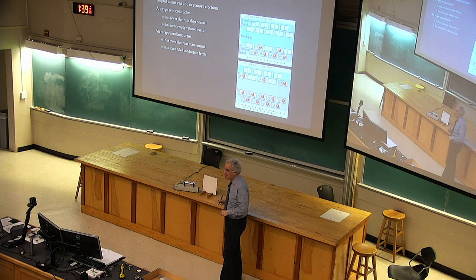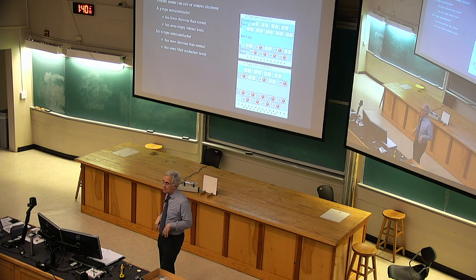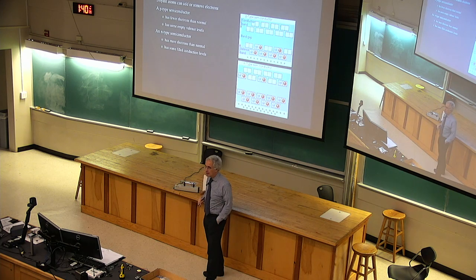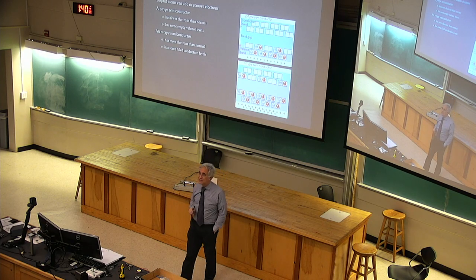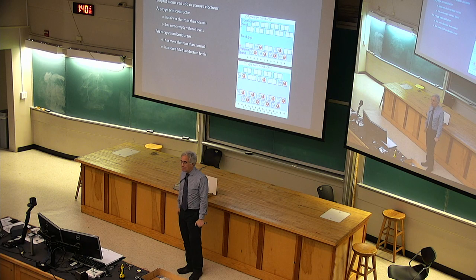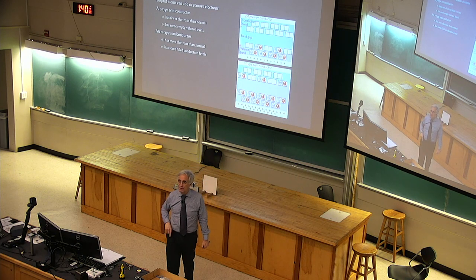All right. What if you start mucking around with the silicon? So I do have silicon in mind when I'm talking about this, but there are other semiconductors, some of which are important and in common use. But we can stick with silicon, it's good enough. If you take silicon and you remove a couple of atoms from the overall solid and you replace them with atoms that have fewer electrons. For example, to the left of silicon in the periodic chart is aluminum. The aluminum atom is very similar to silicon, except it has one fewer proton in its nucleus, and therefore it attracts one fewer electron.